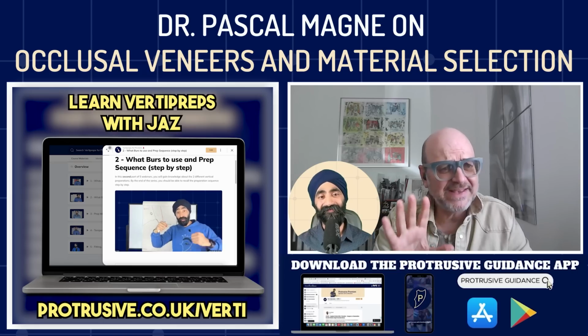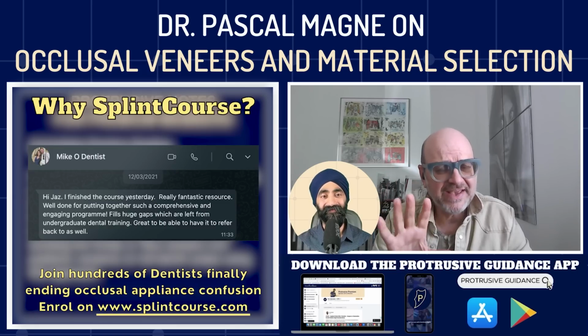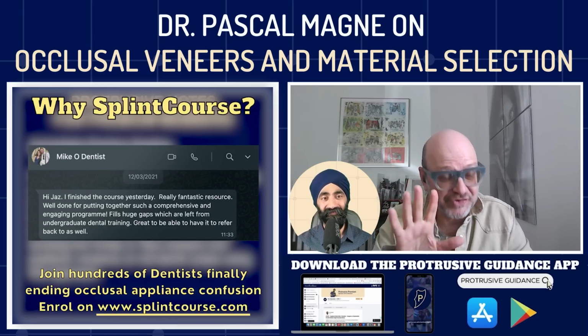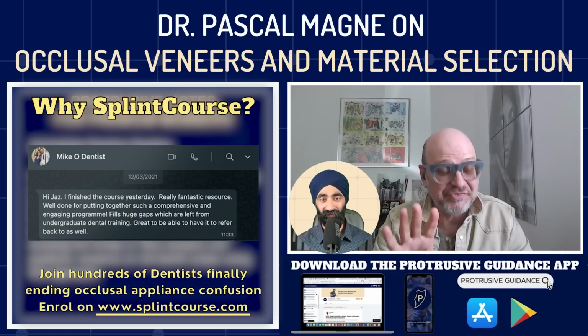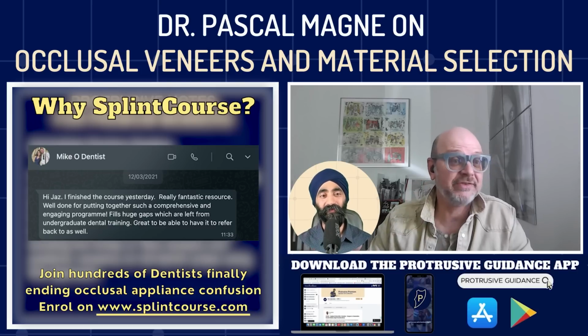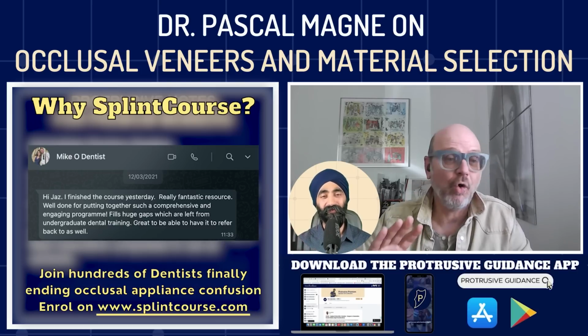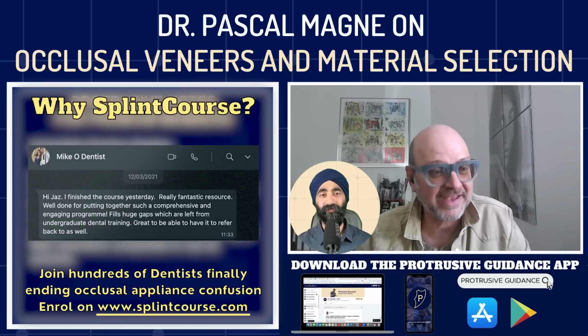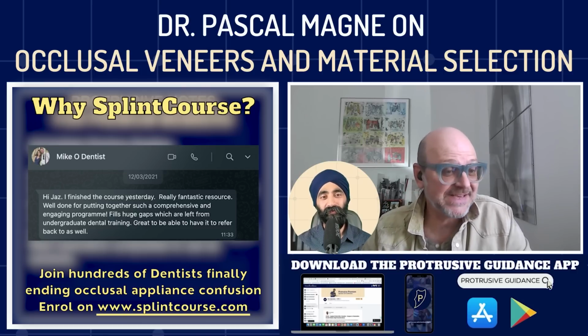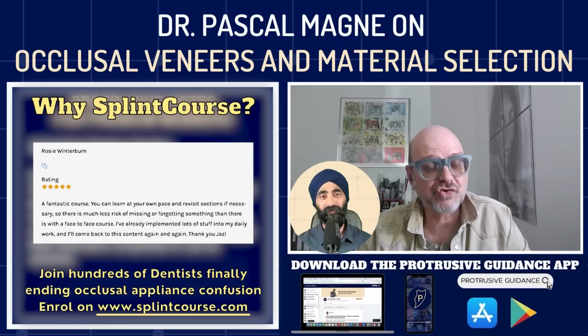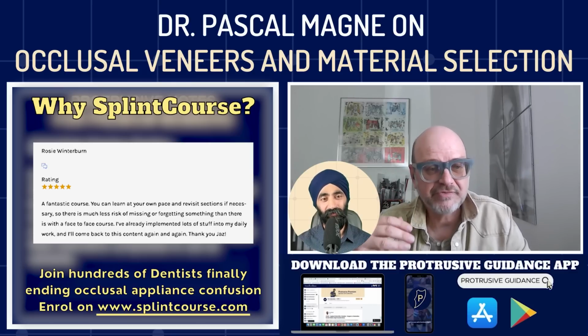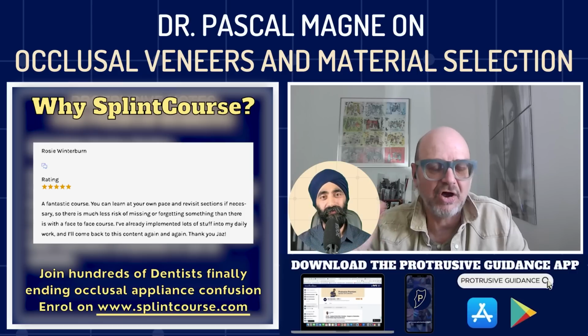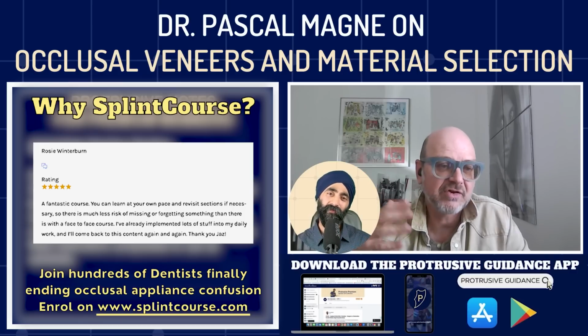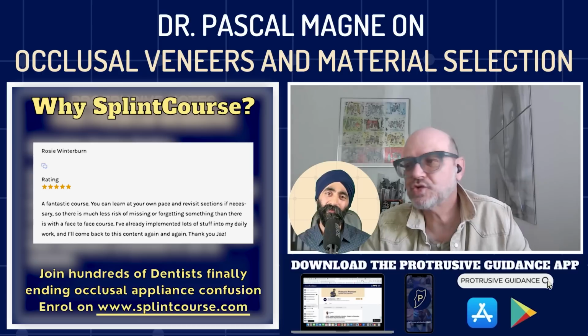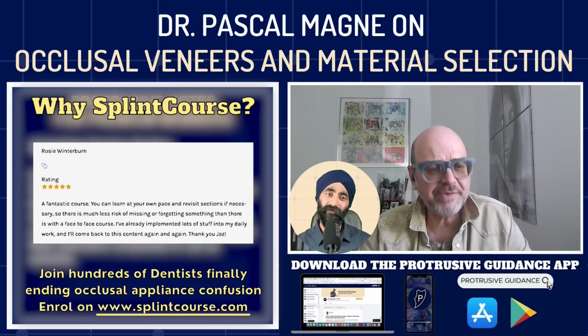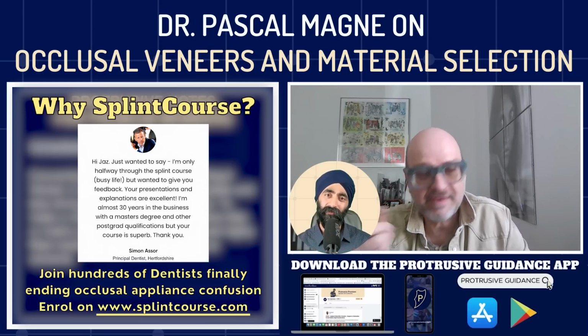And if you do IDS and you bond them with a highly filled restorative, that will be really a difference compared to bonding them with RelyX Veneer or Variolink Esthetic or things like that, which, as I told you, are not as strong because they are flowable. For a material to flow, you have to pay a cost, which is the filler content or the quality of your resin matrix. So those highly filled materials, we preheat them and we use them as cement.